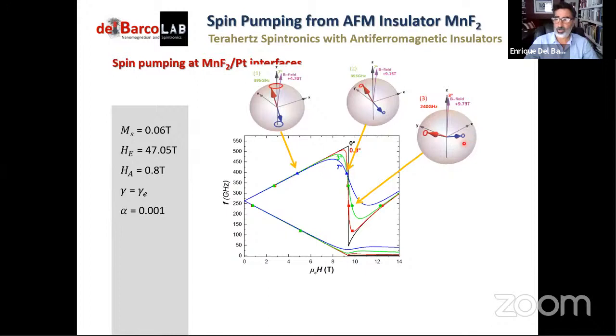And when we go farther in field, and we get deeper into the quasi-ferromagnetic mode, the magnetizations are basically perpendicular to the applied magnetic field, right? But also, the modes start distorting and they become more linearly polarized. And it's important because with a linearly polarized mode, you don't expect spin pumping.